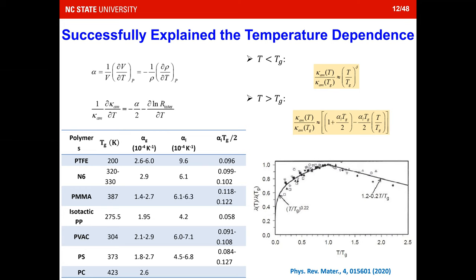When the temperature is below or above the glass transition temperature, you will basically have two experimental approximations, at least on the right part of the screen. And the forms of those two equations actually match pretty well with the experimental data. As you can see, when the temperature is less than the glass transition temperature, you have this T over TG dependence. And then when it's higher than the glass transition temperature, you have this negative linear dependence.